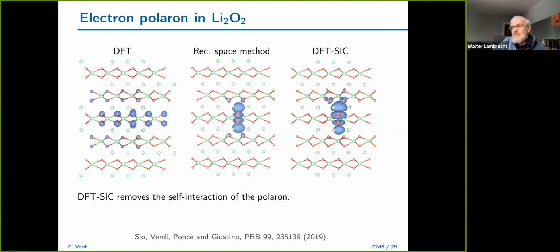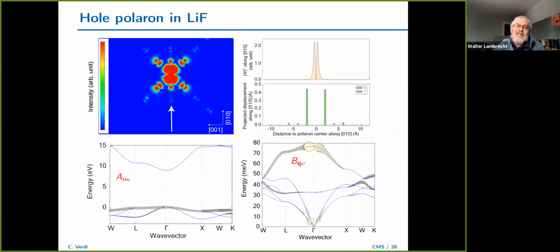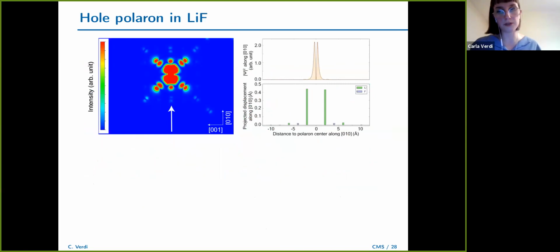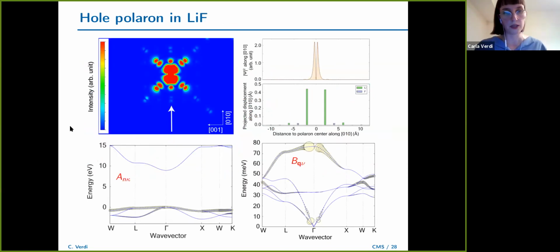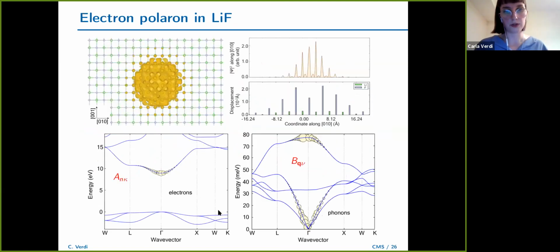Exactly. In your other picture, it shows that it's usually only one band that comes in. So it turns out that yes, there's basically only one band that contributes. Also here. I didn't show these plots for lithium peroxide, but in lithium peroxide you can see that there are two bands that contribute in the same way. So that's actually an interesting thing to observe.